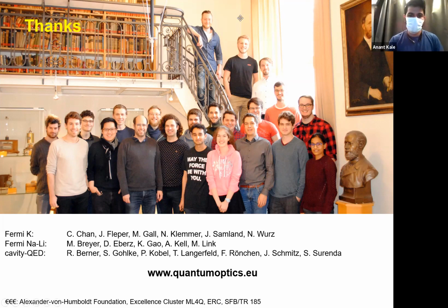Hi, I had a question about the imaging of the bilayers. The correlations that you measured after the spin flip, the ferromagnetic or the antiferromagnetic correlations, were those measured for each layer, or are they the sum of the two layers? No, we measure this for each layer. I see. And they're the same for the two layers. Yeah. I see. And I was just curious how you measure them for the two different layers.